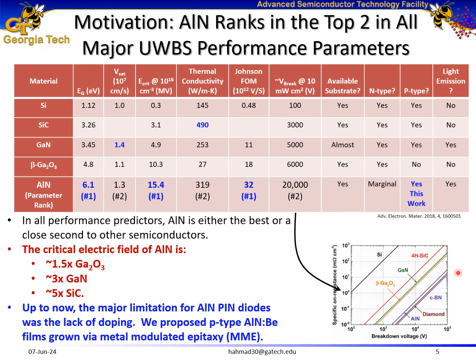My major motivation for this study is that aluminum nitride ranks in the top 2 materials in terms of ultra-wide bandgap semiconductor performance parameter. For example, the critical electric field of aluminum nitride is 1.5 times that of gallium oxide, 3 times that of gallium nitride, and approximately 5 times as compared to that of silicon carbide. But up to now, the major limitation was p-type doping, the lack of doping in aluminum nitride. And we first proposed beryllium doped aluminum nitride p-type films grown via metal modulated epitaxy.